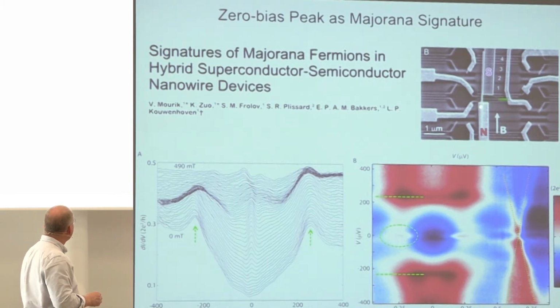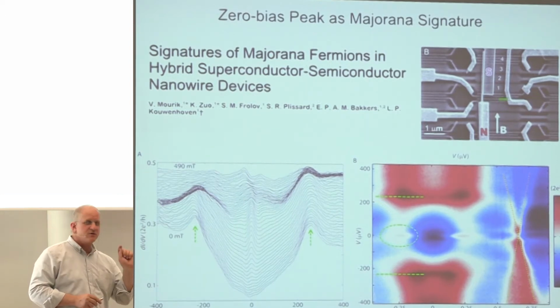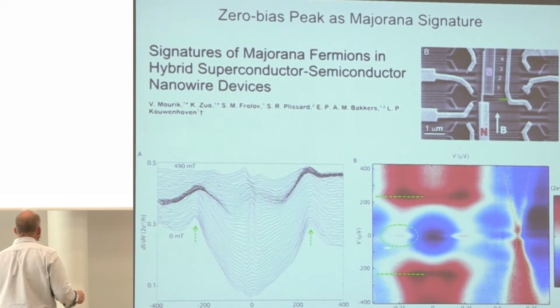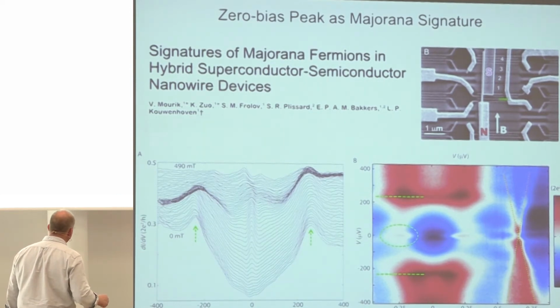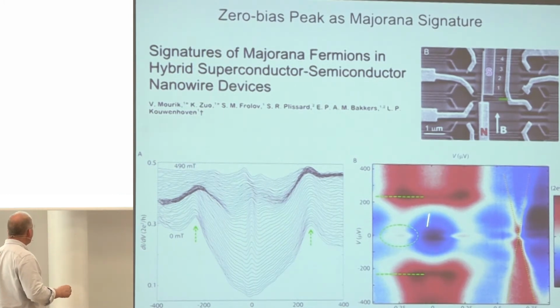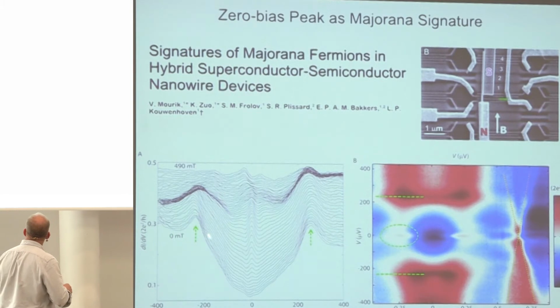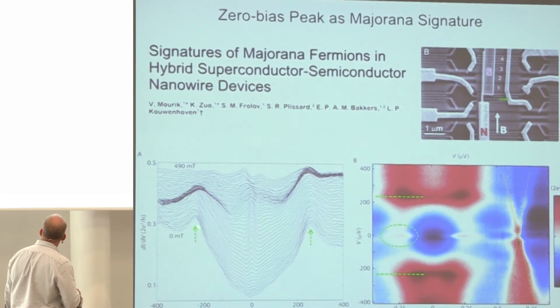And then the tunneling experiment would go into the normal end that you could just tunnel out. That would be a way to provide the normal electrons for the tunneling. And by making these barriers rather opaque, you could find out whether or not you could tunnel a normal electron directly into the superconductor at zero energy. And the experiment indicated that at zero magnetic field, sorry, I chopped off the magnetic field here. This is a magnetic field in Tesla along the horizontal axis. At zero magnetic field, no, you cannot. There was a dark spot in the tunneling density of states indicating that there were no electron states available for tunneling. Here you can see in the zero magnetic field data, below this BCS density of states, this big valley indicating that it's difficult to tunnel in.